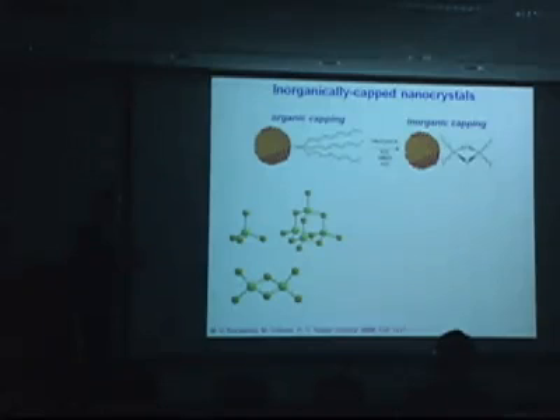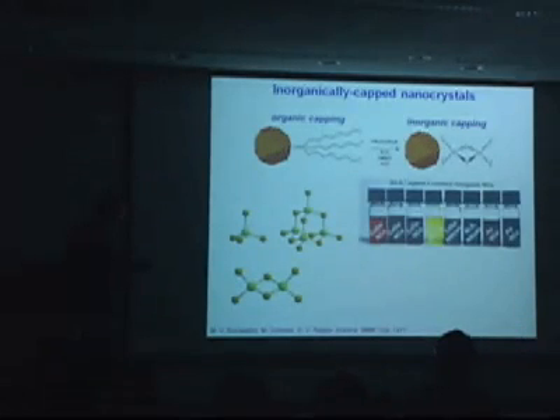In an attempt to address this problem, we decided to redesign or rethink how the colloidal nanoparticle should look. You can go to Wikipedia and look at how people define colloidal nanoparticles. It is defined as an inorganic core surrounded with a shell of organic ligands. But we've been lucky to find a very good replacement for these organic ligands. We found that there is a very large family of inorganic compounds, we call them molecular metal chalcogenide complexes. A large part of this family can be described as Zintl ions. Something like this can perfectly replace organic coating and make colloidal solutions of inorganic nanoparticles, fully inorganic.